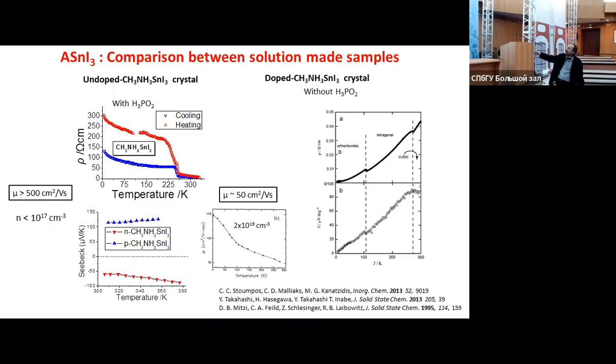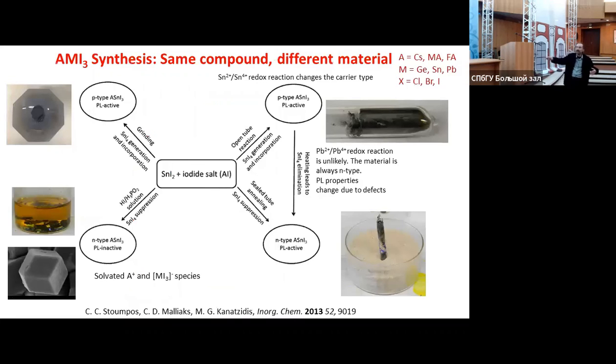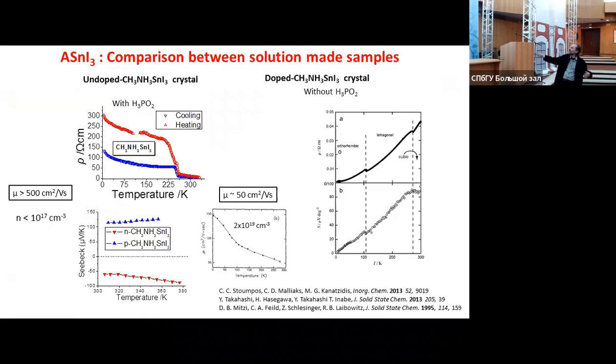But what I can get is probably 2 to 3 orders of magnitude higher. By simply using this one when I make the crystals, because these are crystals made from solution, it's basically this type of crystals. If you use these reducing agents, you prevent oxidation, and that's how you get it to be N-type. How much N-type is unclear, and it changes from synthesis to synthesis. It's hard to control, but you change the behavior at least. You change from this temperature activation to this.